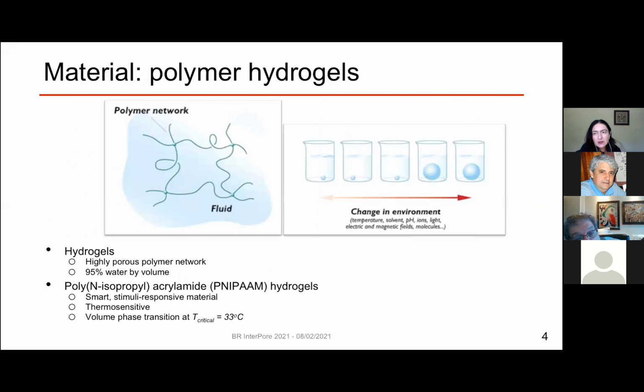The foundation of the material is a hydrogel, and hydrogels are highly porous polymer networks that hold about 95% of water by volume. The one that we're using in this work is called poly(N-isopropylacrylamide), or PNIPAM hydrogel. That is a smart stimuli-responsive material. It has a very interesting property, the volume phase transition: at the critical temperature of 33 degrees, if you go above it, the gel collapses and expels all the water, and the volume is much smaller than what it used to be. Below the critical transition temperature of 33 degrees centigrade, the gel starts absorbing water and it becomes bigger and bigger and bigger.